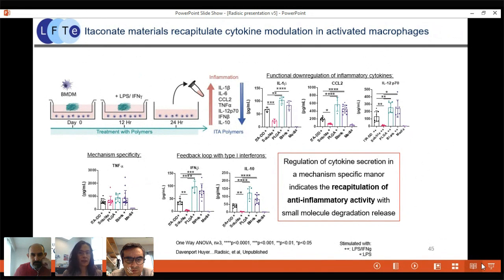So one representative control is widely used polyesters, such as PLGA, and you can see that in a number of these important cytokines, itaconate-containing materials, as well as soluble itaconate, really downregulated secretion of inflammatory molecules in these activated macrophages. And we can see very similar, strong response on PLGA, basically in all of these materials.